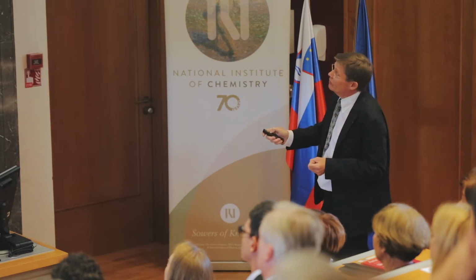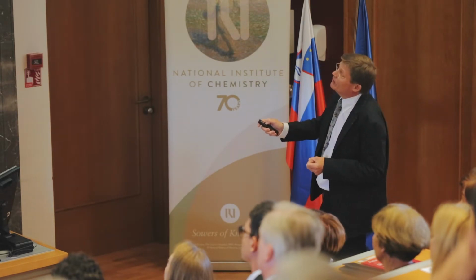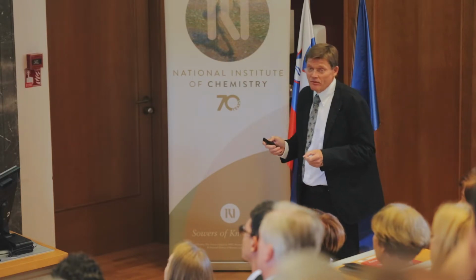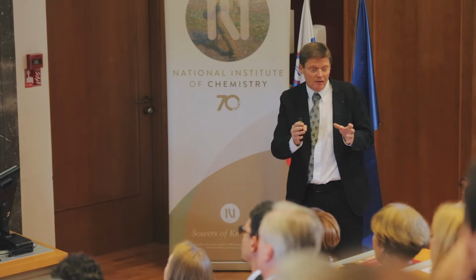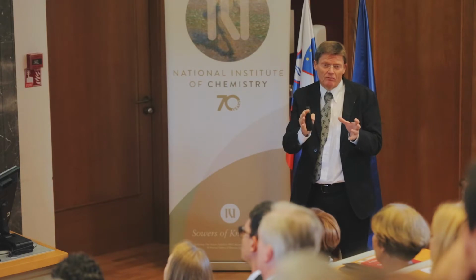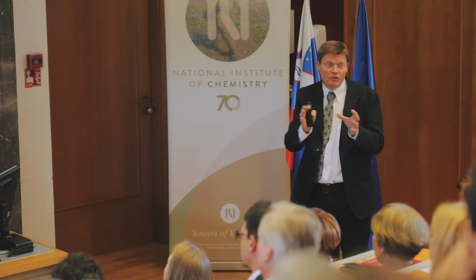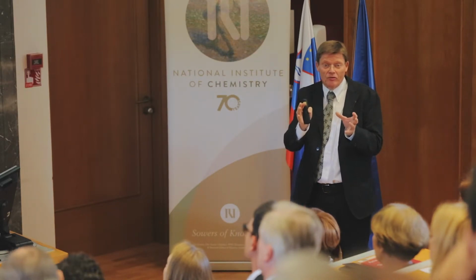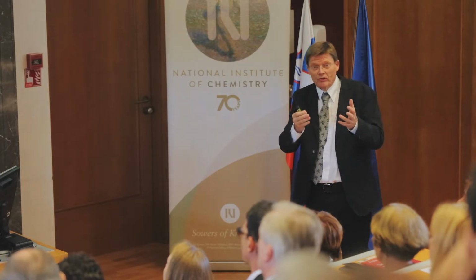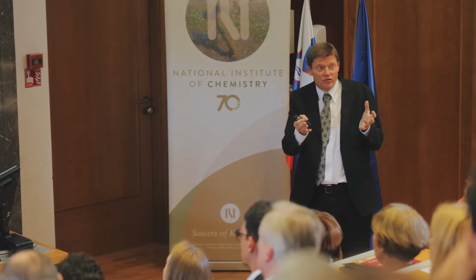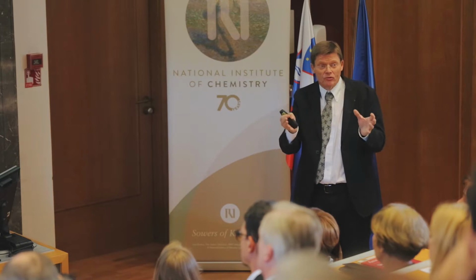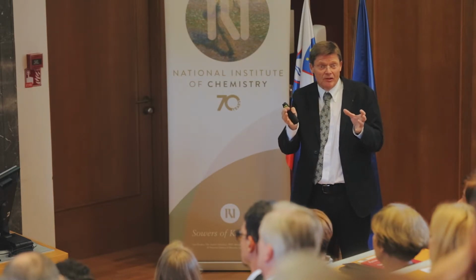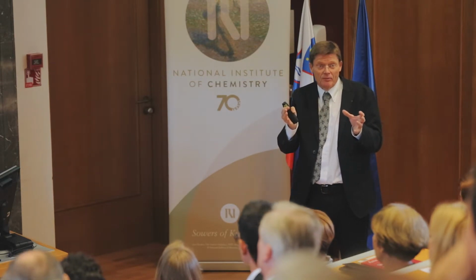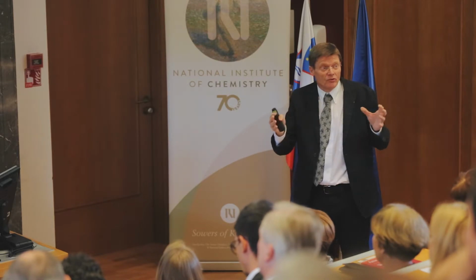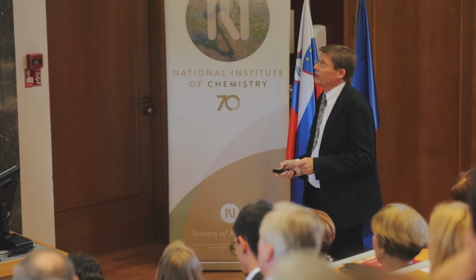When you switch off the current, everything goes back. The time dependence is determined by the so-called chemical diffusion coefficient. It's the most important diffusion coefficient that you have in terms of chemistry. Whenever something is transport controlled, and you change your composition, then it's a chemical diffusion coefficient. This depends on ions and on electrons. Both have to cooperate.